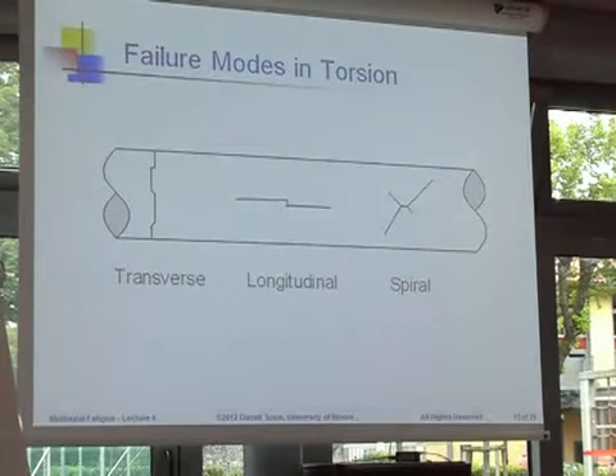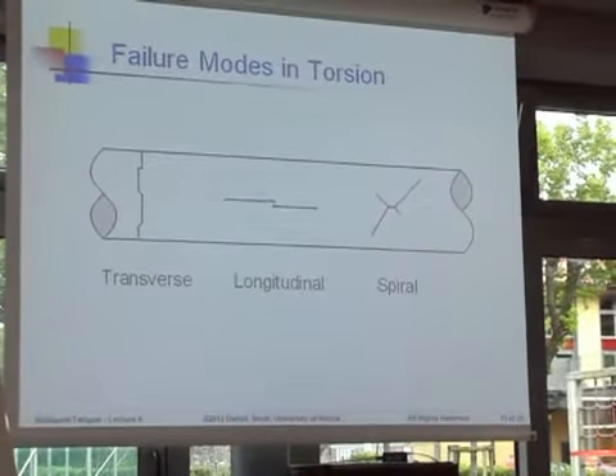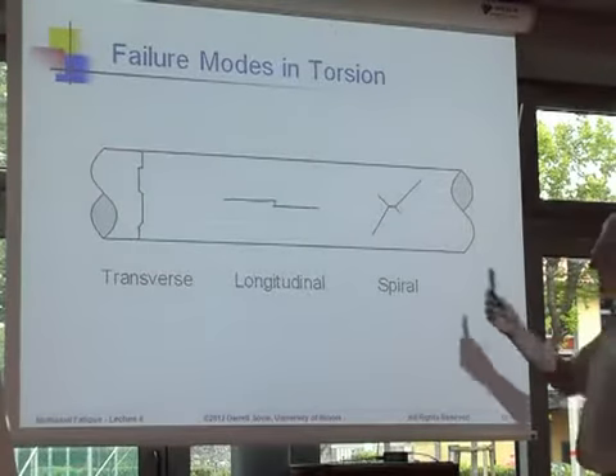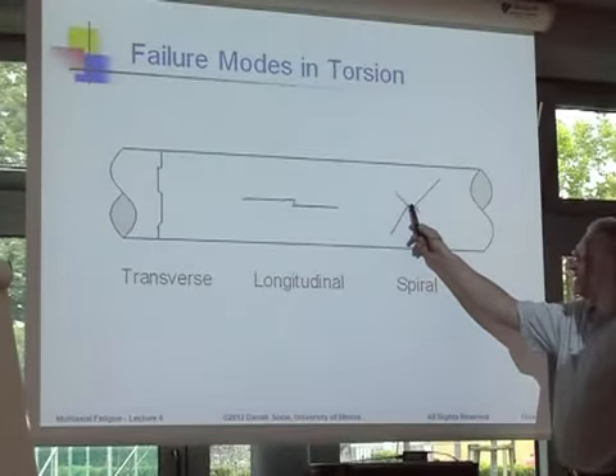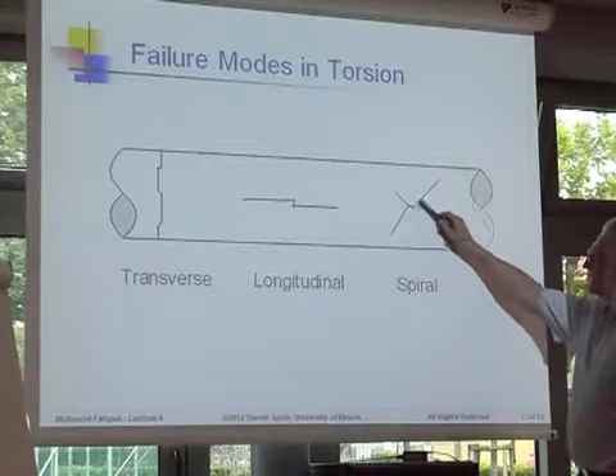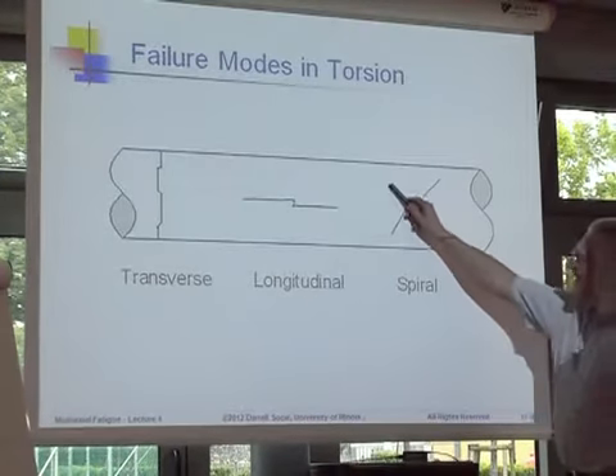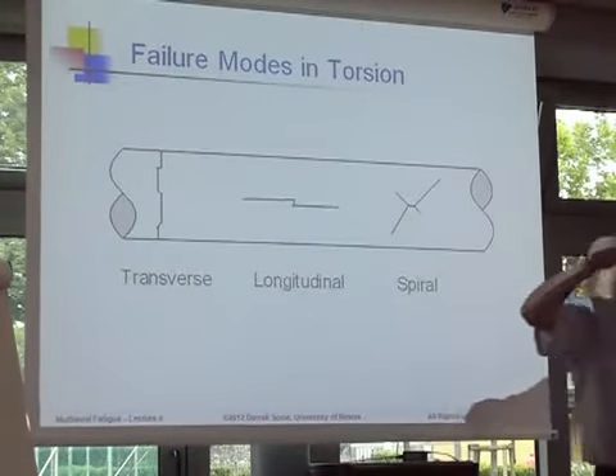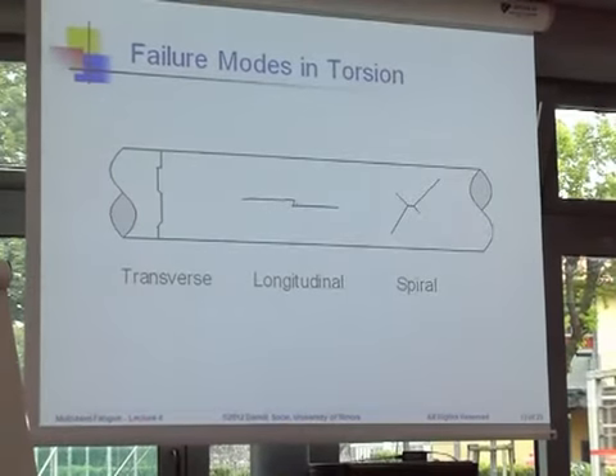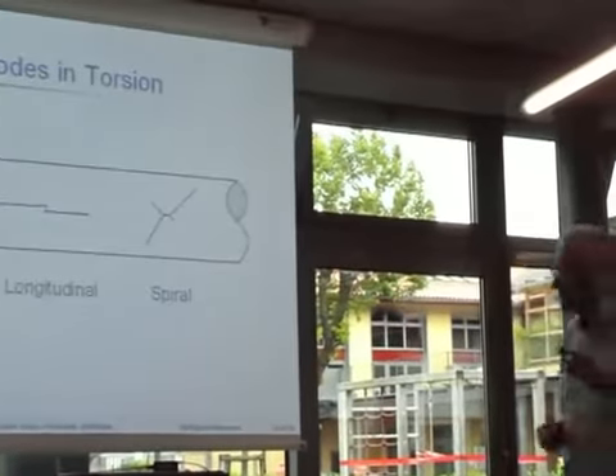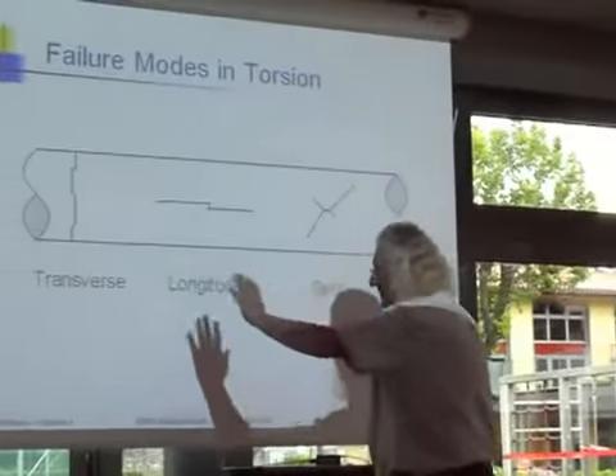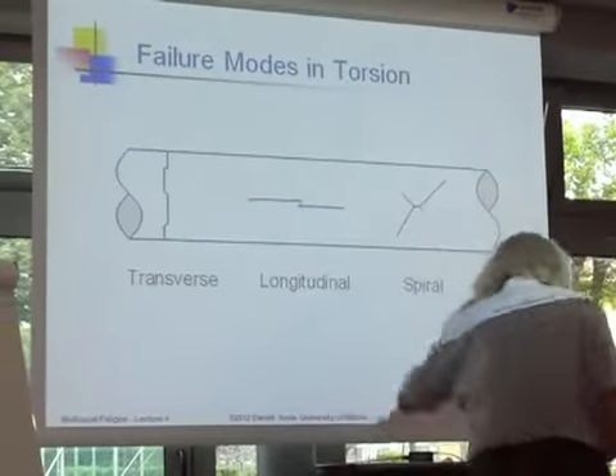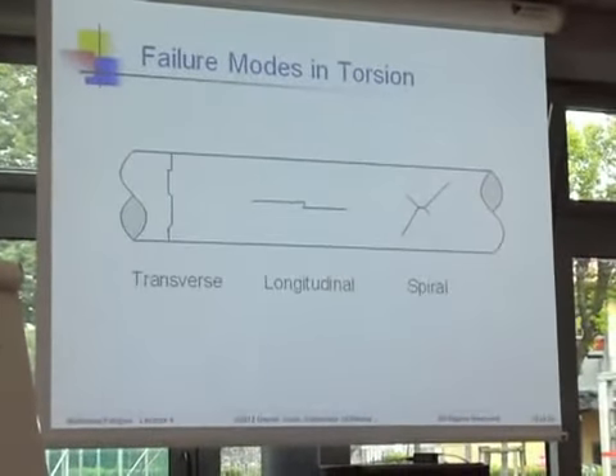And finally, if I have a torsion test at a very, very long life, the cracks always nucleate in shear, and then they turn to grow into mode 1, and they spiral around. And this is always the order of failures. The failure mode is very different with stress amplitude. I'll show you some examples.